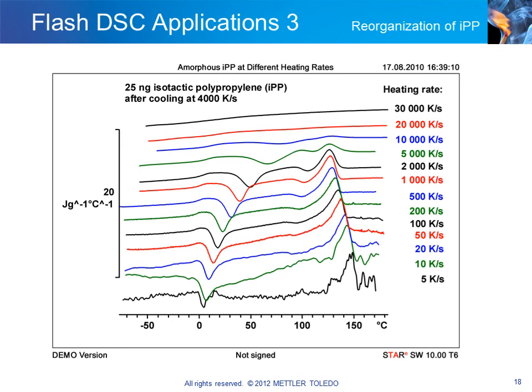The curves show that with increasing heating rate, the crystallization peak shifts to higher temperatures and the melting peak to lower temperatures. At heating rates above 2000 degrees per second, the areas of the crystallization and melting peaks start to become smaller. At about 30,000 degrees per second, crystallization no longer occurs. Even on heating, the material remains amorphous and exhibits only a glass transition.